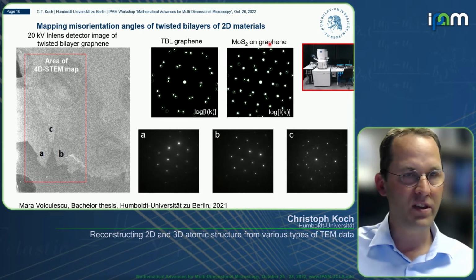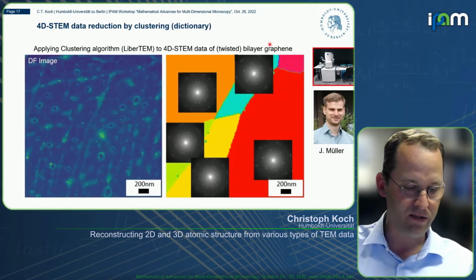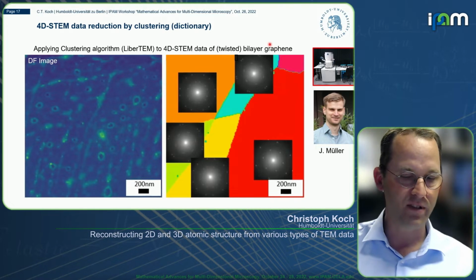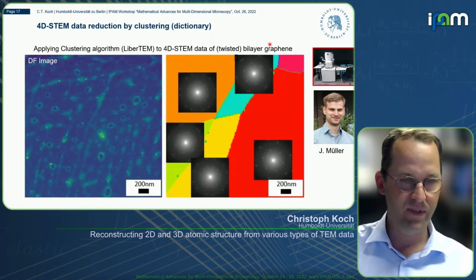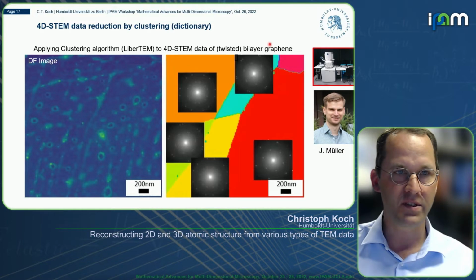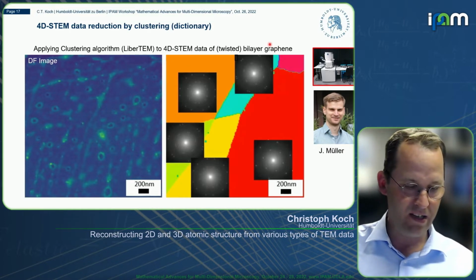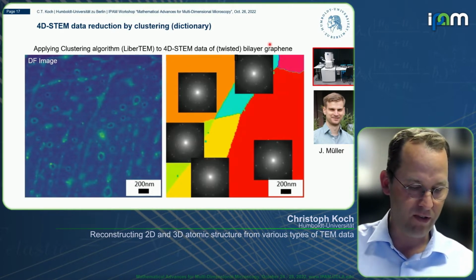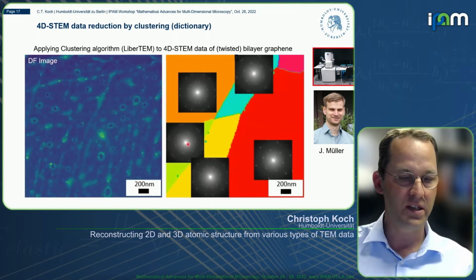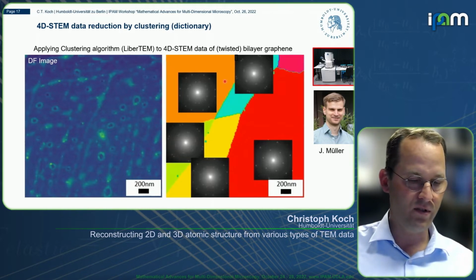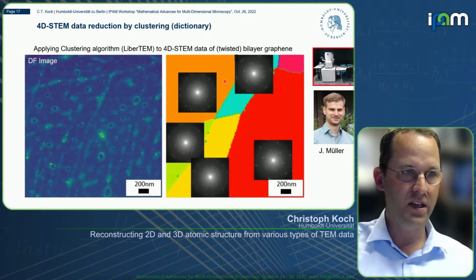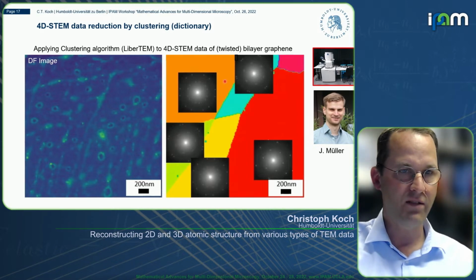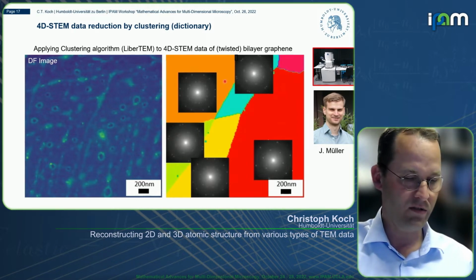And for example, if you buy one of these twisted bilayer graphene materials, as we did here, this is a commercial sample, and you have to be careful. They may tell you, oh, this material has, for example, a twist angle of 8 degrees. Well, it doesn't quite, because you have many domains with different twist angles. Single domains here, as you can see, there's no double layer, but all the other ones here are 2 layers, and they have all kinds of twist angles between them. So if you don't look at it microscopically, you may not know really what you have when you do your experiment with these kind of materials.